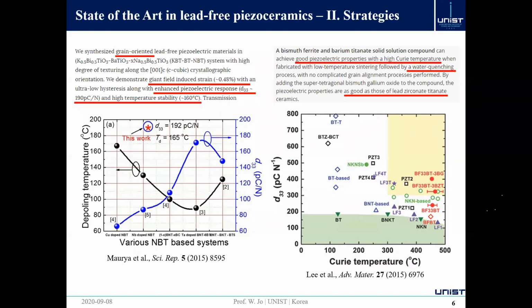For example, grain-oriented lead-free piezoceramics through templated grain growth. The idea is really simple. When it comes to piezoelectric materials, a single crystal should have the best properties because all the spontaneous polarization aligns along the same crystallographic direction, which gives the best performance of piezoelectric materials.